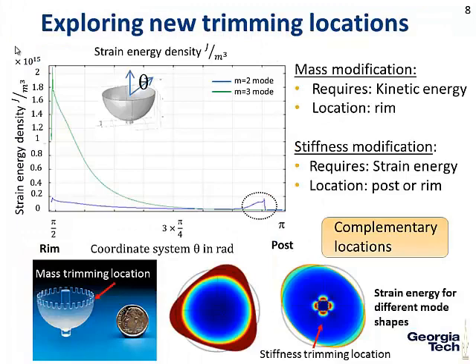As I said, we are looking at new trimming locations. At Northrop Grumman, where they're fabricating their device, they have those little spikes here, and they can do their mass modification either on the top or on the bottom. In our case, what we discovered is that by looking at mass and stiffness trimming, we can actually have two different locations where we can do our trimming. We can either do it at the rim, because here there is strain energy, or we can do it at the post, because there's strain energy here.